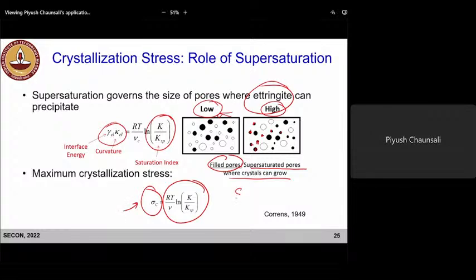Okay, and we can compare in situations. For example, I told you earlier, when we are talking about the exposure solution, when we had a supersaturated solution of gypsum, that led to an increase in expansion compared to undersaturated solution of gypsum. This is primarily because the supersaturated solution of gypsum had higher saturation index. Okay, so we know that now this is the mechanism. Supersaturation is driving crystallization, and then these crystals are precipitating in the pores. When they precipitate in smaller pores, it induces higher crystallization stresses.